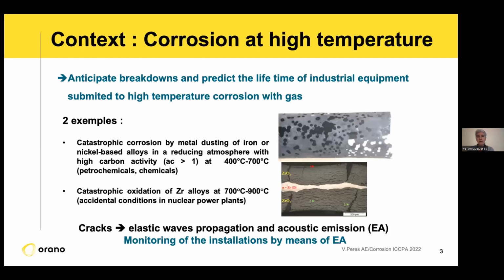For the context, we were asked by some industrial partners to study the high temperature corrosion of their equipment, to anticipate as much as we can the breakdown of this equipment due to corrosion, and to predict if possible the lifetime of this equipment. I show you in these pictures 2 examples. The first one is a catastrophic corrosion by metal dusting of tubes in the petrochemical industry under reducing atmosphere at high temperature. You can see some holes in these tubes, and these are very detrimental conditions.